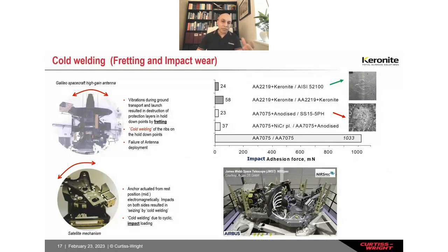It failed during deployment because of the cold welding phenomenon occurred by fretting. And what is fretting? It is the process that occurs at the contact area between two materials under load, subject to relative motion by vibrations. So what happened here is the vibration during ground transport and launch resulted in destruction of the protection layers and hold down points by fretting, and subsequently the contacts welded.